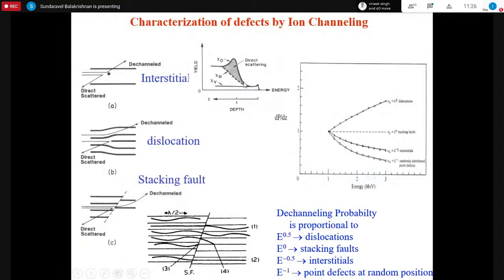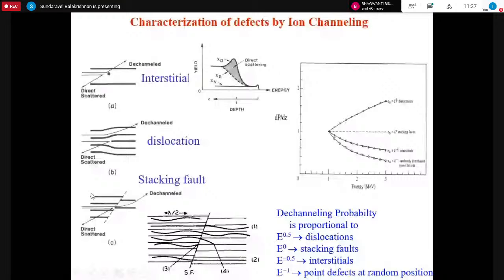And if you look at the ion implanted samples, this one here is the unimplanted sample. But in an implanted sample, if you see the channeling spectra, you see slightly higher yield. And in this yield, there are two components. Whatever is seen with the dotted line corresponds to dechanneling, while the other one is coming from direct scattering. When the beam is scattered by point defects or dislocations or stacking faults, it gets dechanneled. And we study that dechanneling as a function of energy.